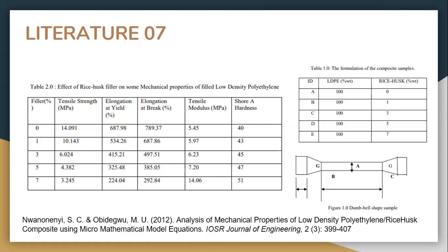In testing the tensile strength, it was found out that at 0% weight fraction addition of the rice husk filler, the low-density polyethylene sample has a tensile strength of around 14 megapascals, reduced to 10 megapascals upon addition of 1% weight fraction, and continuously decreased upon further addition of the filler. Likewise, inverse proportion was also observed between the percent elongation and addition of rice husk fillers. At 0% weight fraction, the LDPE sample has percent elongation at yield of around 688% and at break 789%. This then decreased to values of 534% and 688% respectively upon addition of 1% weight fraction and further decreased as well upon further addition of the filler.